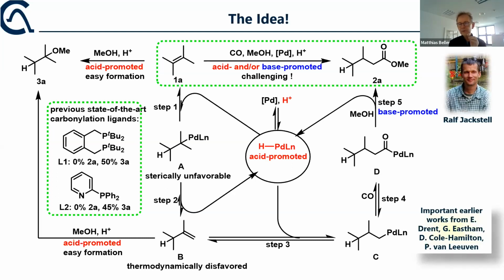So in order to develop a catalyst more rationally, you should understand what is the limitation of the existing catalysts and the chemistry. And if you look at the carbonylation of tetrasubstituted olefins, then it's clear that the carbonylation of the internal carbon is very difficult, because very few stable internal metal-carbon species are known. I'm showing this here for palladium, but for other metals it's true as well. On the other hand, this type of terminal metal-carbon species is much more well known, and there are hundreds of examples. So although it looks very similar, with only a small difference, this is very well established. This is not existing, at least it has not been proven in a stable form.